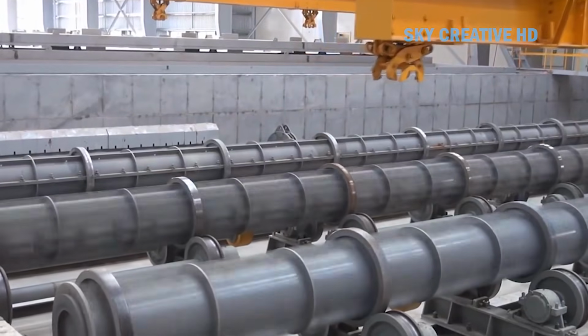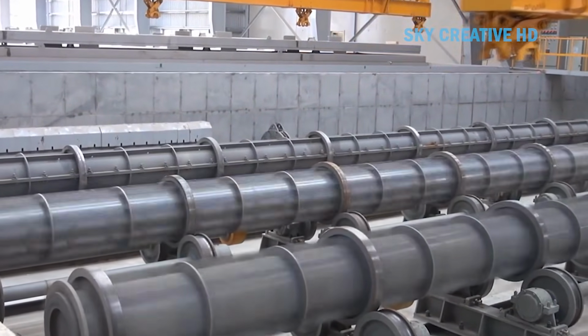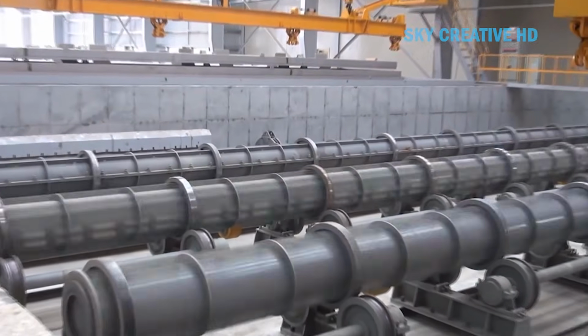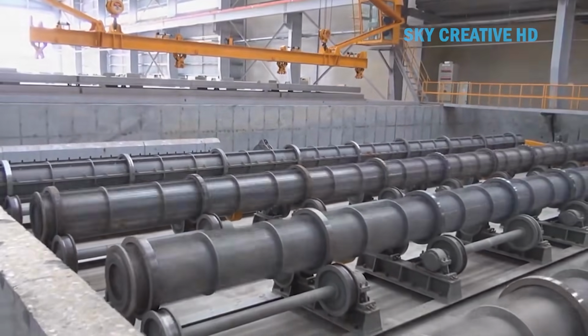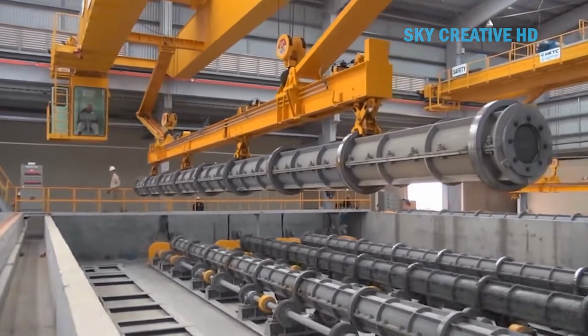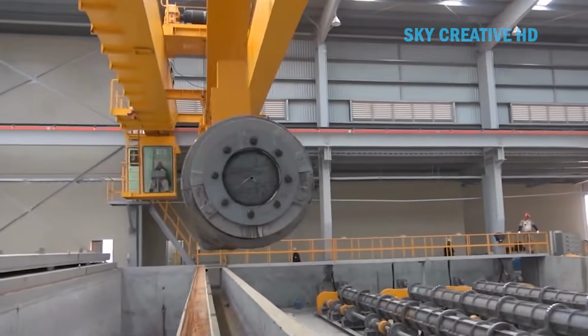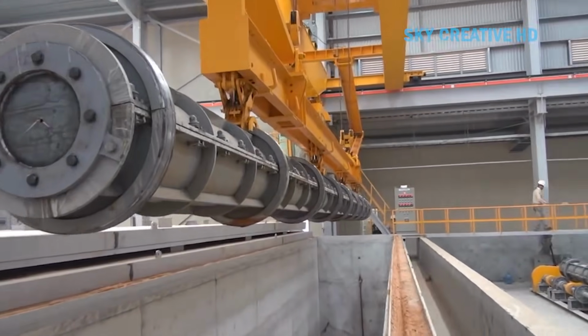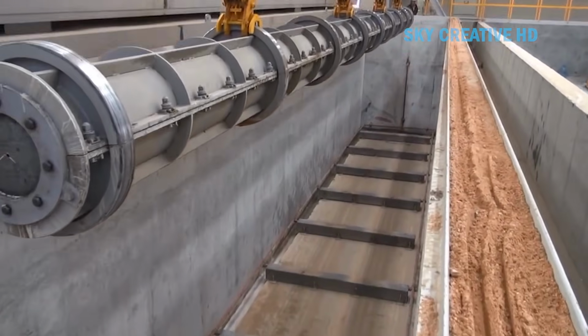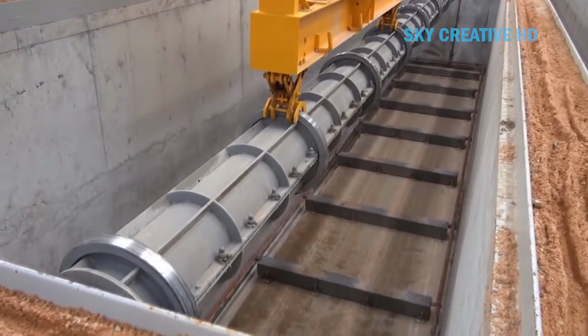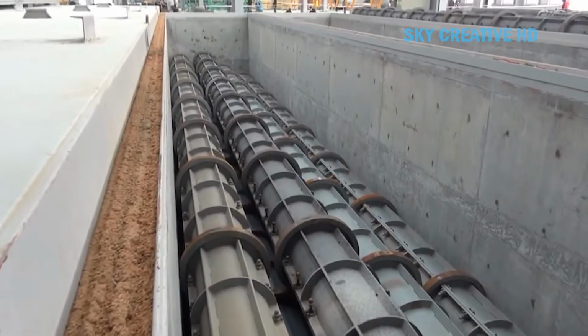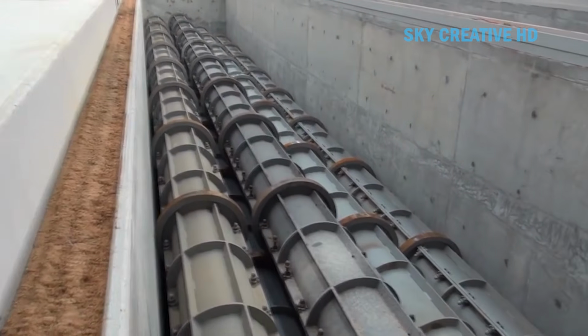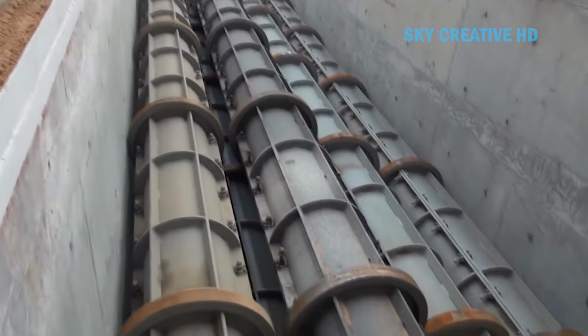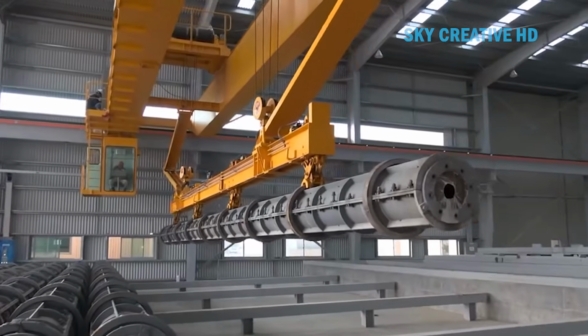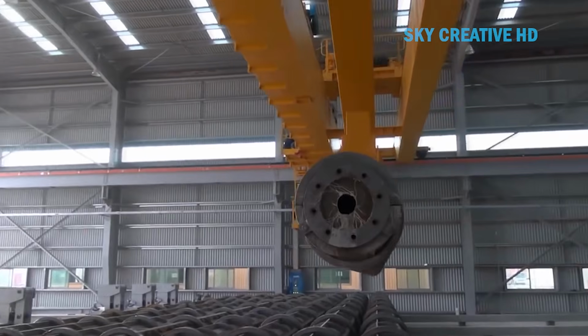The rotary molding process is truly mesmerizing to watch. The entire pile assembly rotates while the concrete is still plastic, using centrifugal force to achieve uniform density and eliminate any remaining air bubbles. This process, borrowed from pipe manufacturing, ensures that these piles have consistent strength properties throughout their entire cross-section. The 12-hour steam curing cycle represents a perfect balance of time, temperature, and humidity.